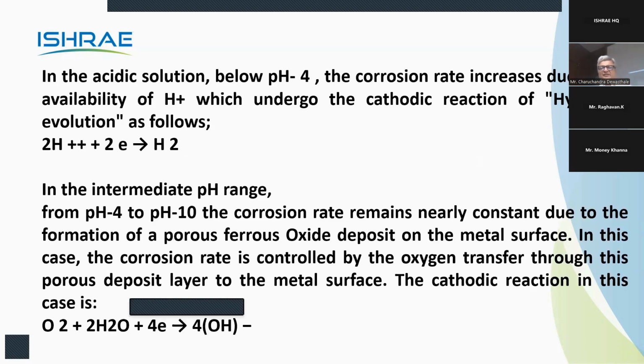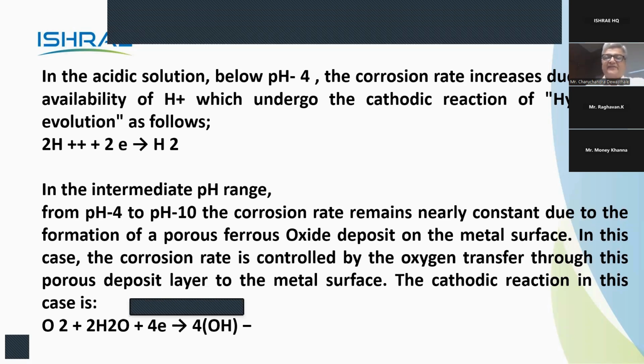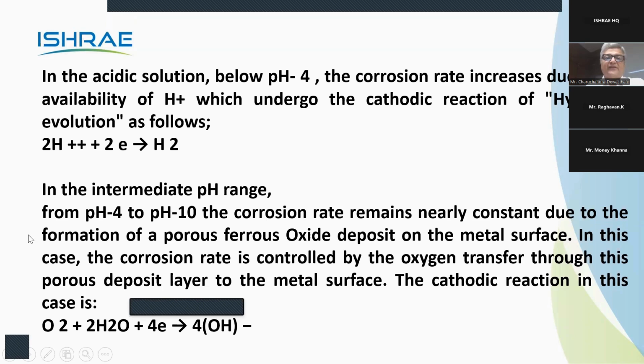In the acidic solution, when the pH is below 4, the corrosion rate increases due to availability of H+ ions, which undergo cathodic reaction of hydrogen evolution, and H2 will be formed. In the intermediate pH range, from pH 4 to 10, the corrosion rate remains nearly constant due to formation of porous ferrous oxide on the metal surface. In this case, the corrosion rate is controlled by oxygen transfer through this porous deposit layer to the metal surface. The cathodic reaction forms a hydroxide.